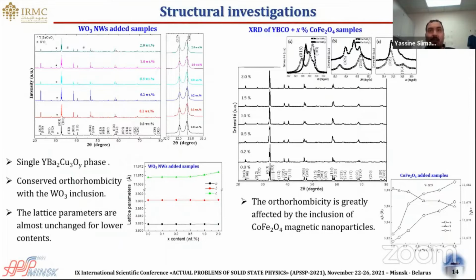These are some of the recorded XRD patterns for YBCO superconductors added with different amounts of tungsten oxide nano entities having nanowire shapes and magnetic nanoparticles of cobalt ferrite. As is clear here, predominantly single YBCO phase with orthorhombic structure was observed in all synthesized products, confirming the successful preparation of the desired composition.